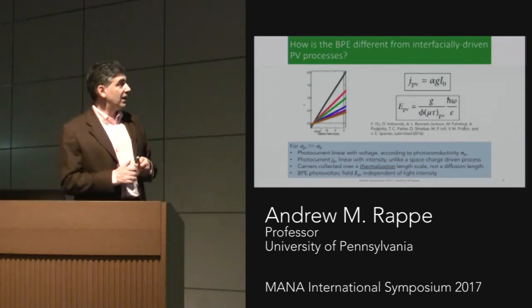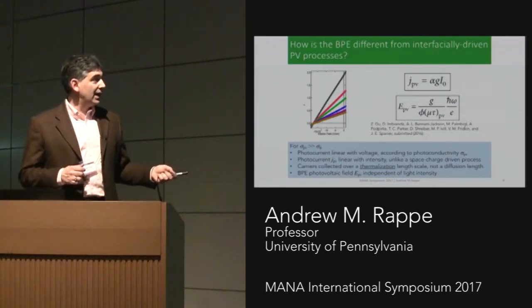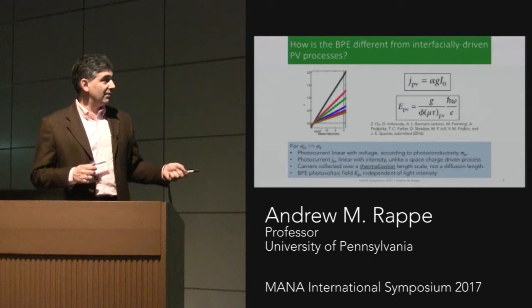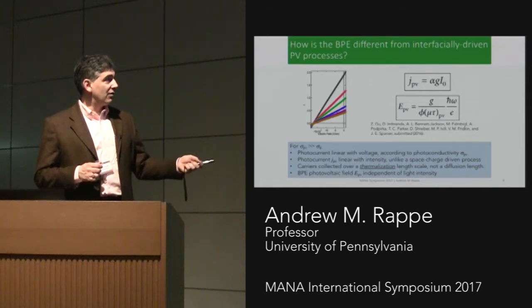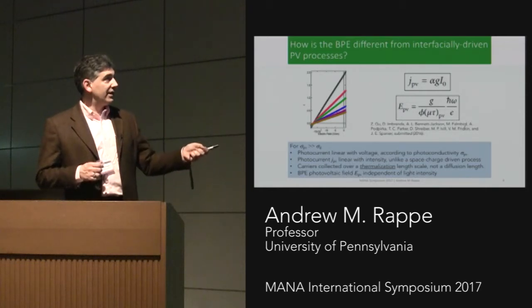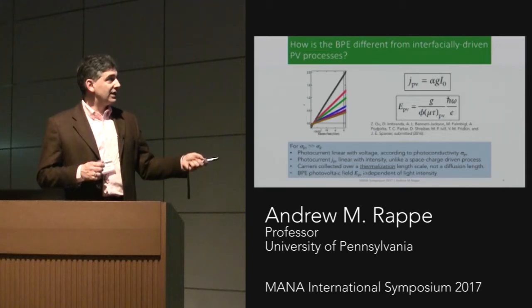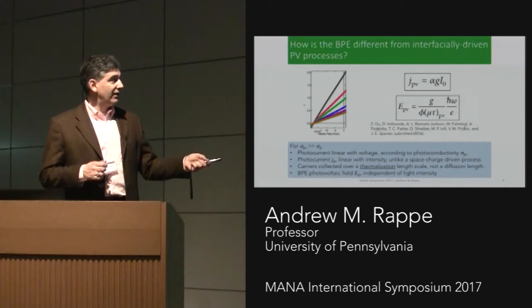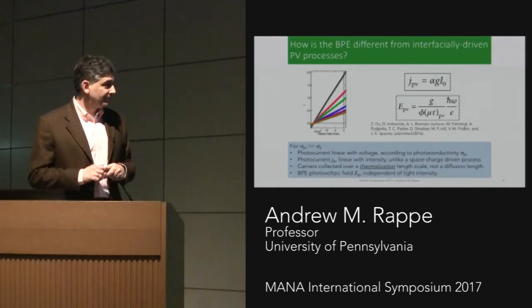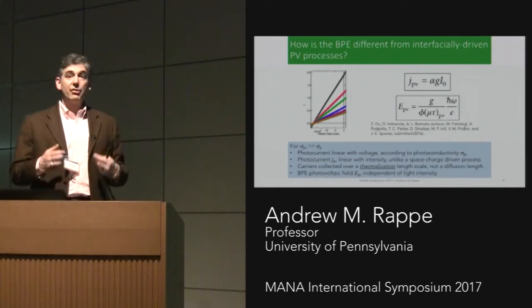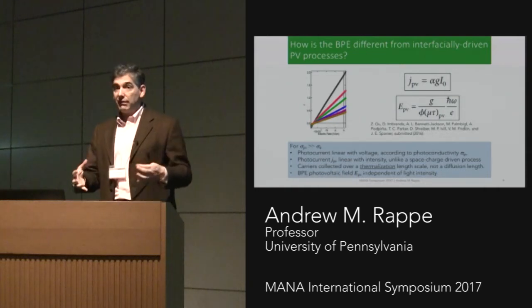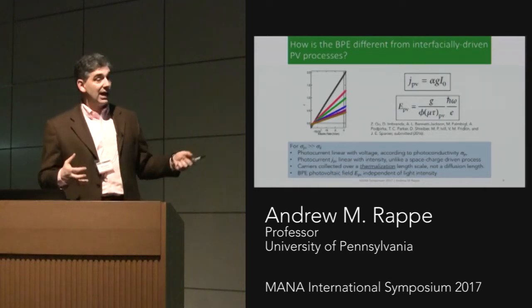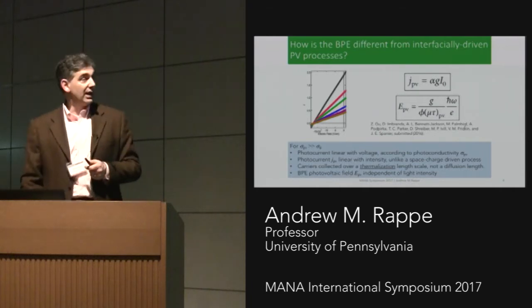Okay, and so this is a recent result by my friend and collaborator Jonathan Spanier with Vladimir Fridkin, again showing current versus electric field as linear, and all of them cross zero at the same point. So as you vary the light intensity, you get the same photovoltaic field and voltage. Okay, so this leads to the hypothesis that the current is traveling for only a finite distance as a hot carrier, as I showed you on the previous slide.